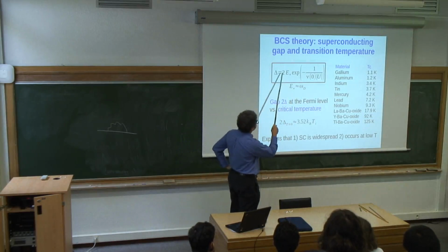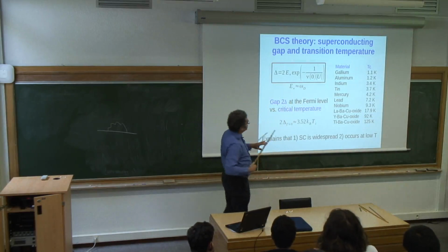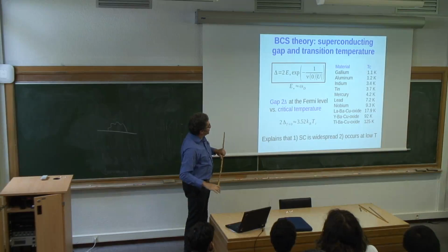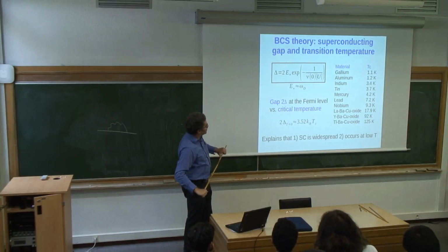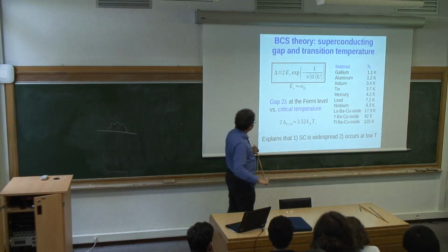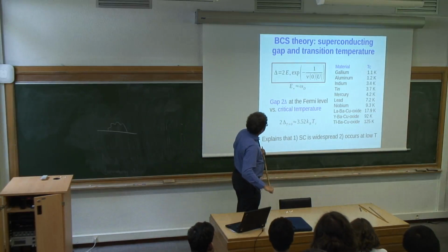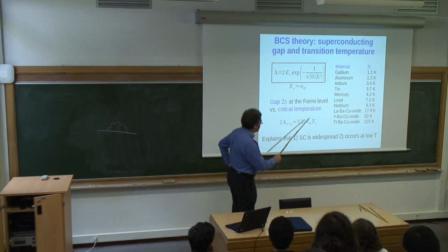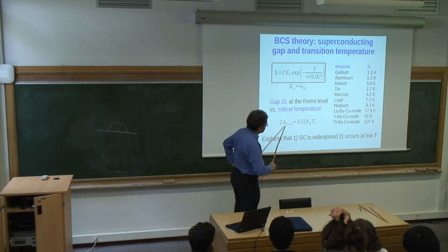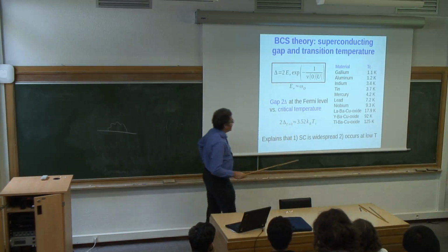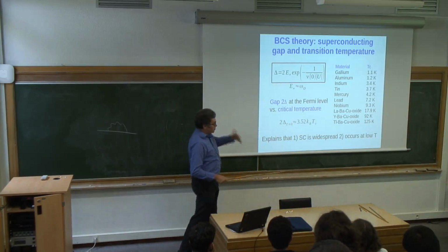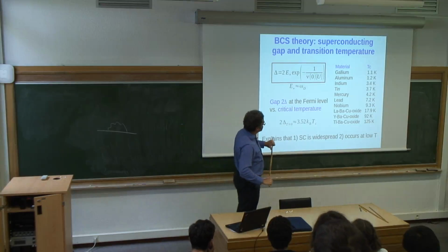And the prefactor is of order of Debye's frequency, because it's phonons that produce attraction in the first place. And so that's the result for the energy gap. The result for critical temperature is that there is a universal relation between the energy gap at zero temperature and critical temperature at which the superconductivity disappears.